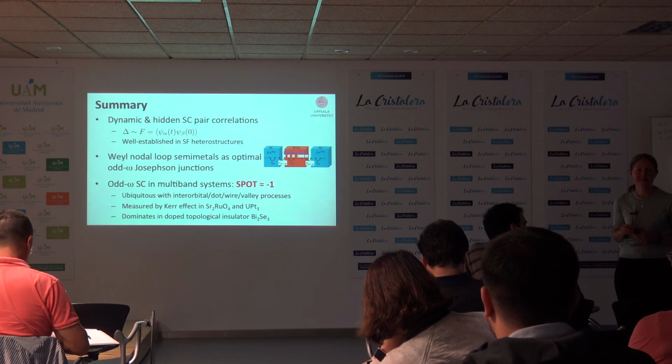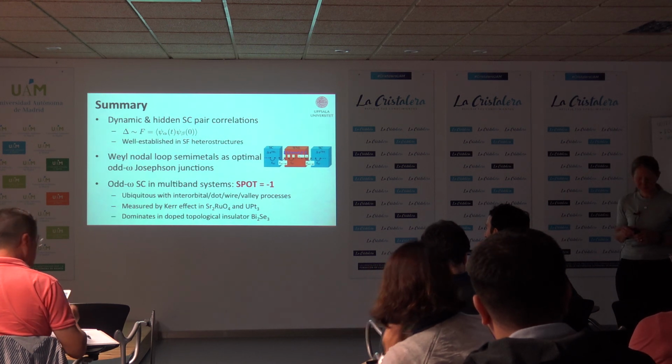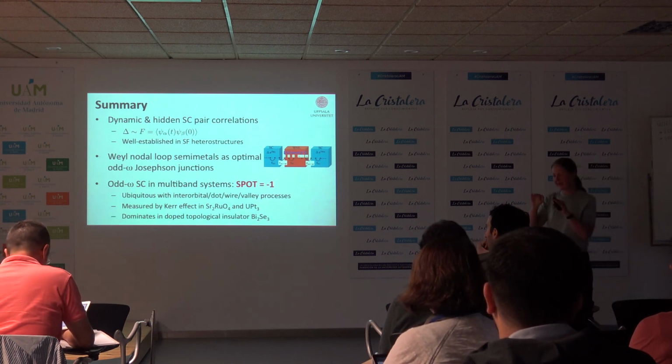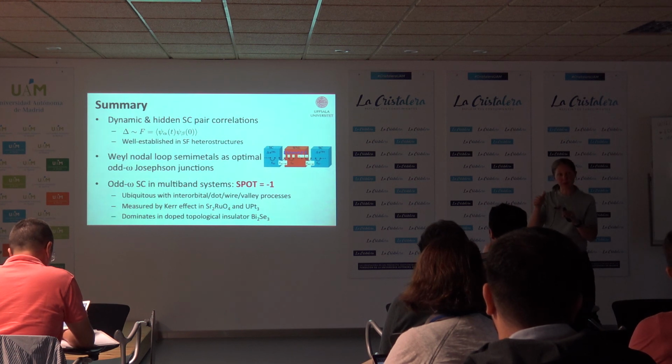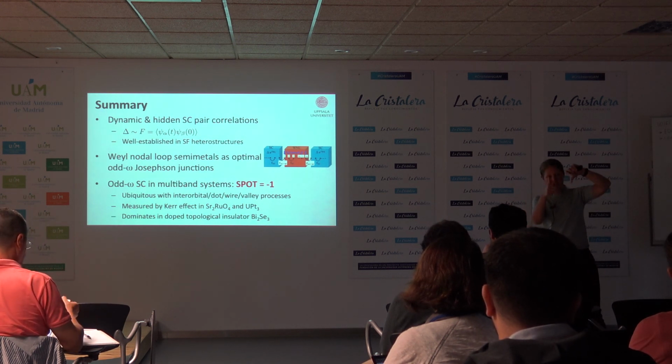In order for the spin triplet component to survive through the interface, does it need to be coupled with the spin orbit? I didn't understand that very well. Yes, so what happens if you just have an SF interface, so you just have one magnetization direction, the most you can get is the spin singlet transferring into the spin triplet with mixed spins, the so-called zero channel, a spin triplet that still looks like this.